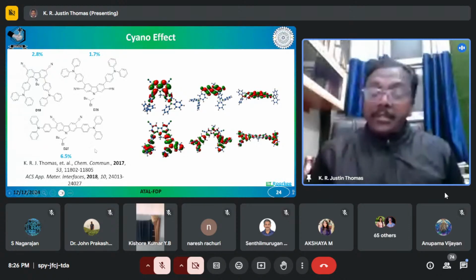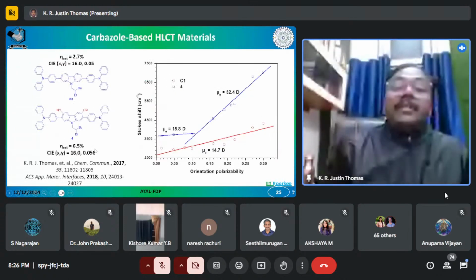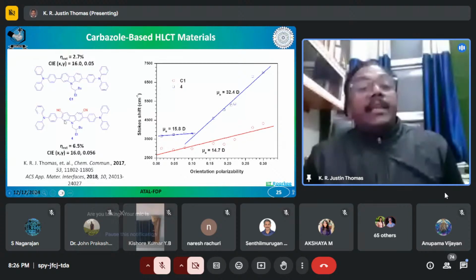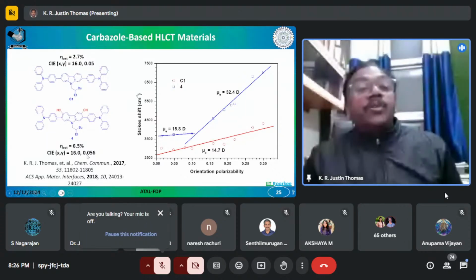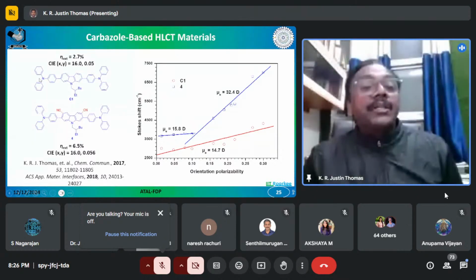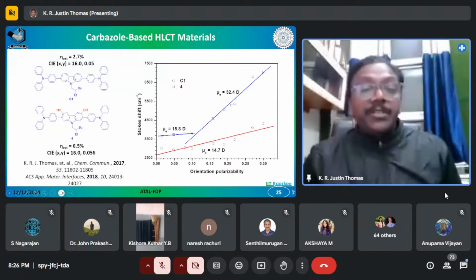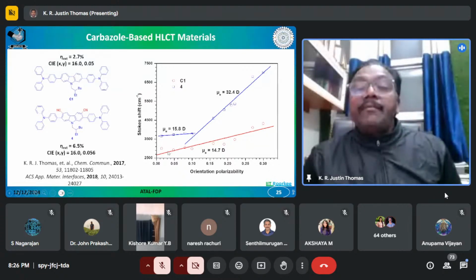That is coming from the hybridization of local and excited state. And particularly comparing these two molecules will give more meaningful insights. You can see here there is no cyano group, there is no electron withdrawing group. So that means that there is no charge transfer. That is having a very weak line in the Lippert-Mataga plot.